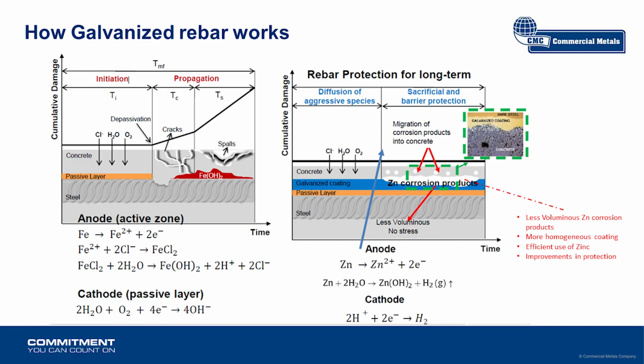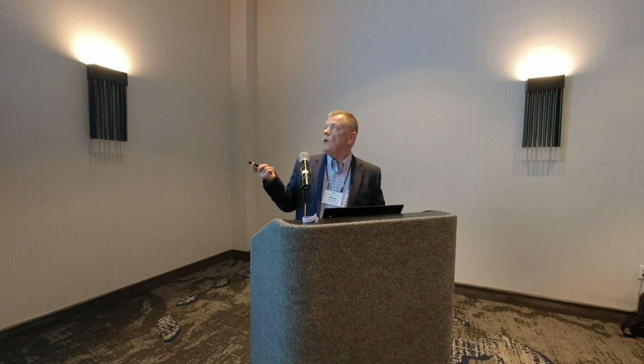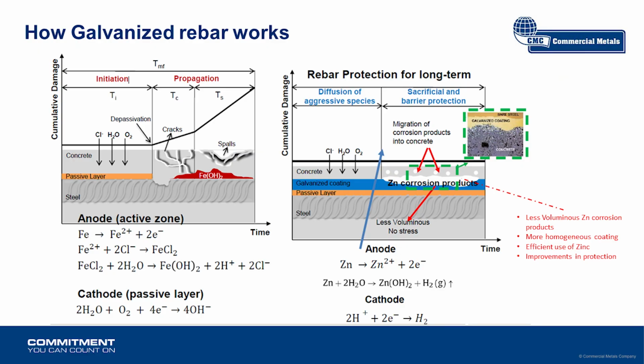Just a quick graphic on how galvanizing works. You have this initiation phase where the chlorides are coming into the concrete matrix, creates the cracks, and then you have a propagation that occurs after the passivation breaks down, and it's able to increase, oxides start growing on the metal, and that'll create the spalling after the volume is increased. And so whenever you have zinc on the zinc coating, what occurs here is once the critical chloride threshold is met, then you have these zinc ions that are migrating away from the matrix, and they're less voluminous, and so they're going to infill those pores, and actually densifies the concrete.